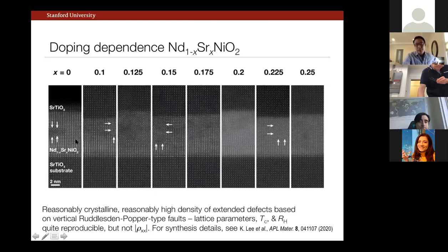And this is trying to be fairly representative, meaning there are stretches of these films that are nicely coherent, but there's a fairly high density of defects, extended defects. So you can see this box here, for example. If you're interested in these details, we've described them in some detail in this paper by Kyuho.